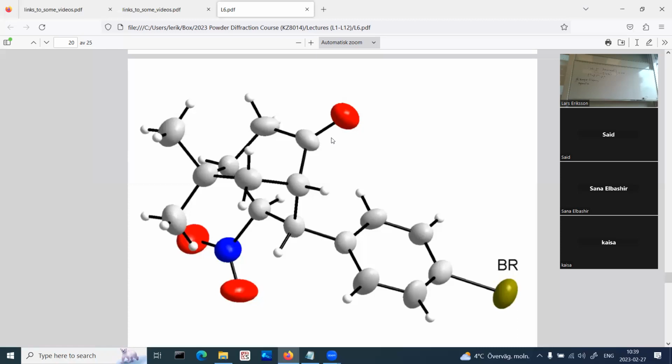I would recommend to always try to combine with X-rays. If you're into a neutron structure, solving it is usually easier from X-ray, because we have different scattering efficiency for X-rays and there are heavy atoms, for example a metal in an organic compound.